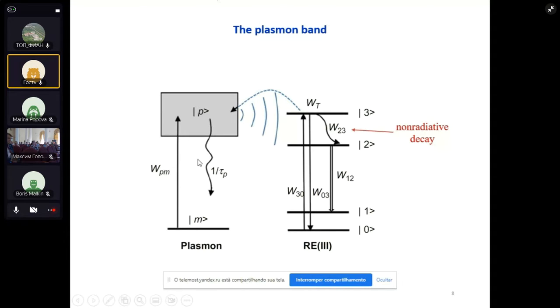And you may ask, why not energy transfer from the plasmon band to the emitting ion? It's because in an appropriate system of rate equations, you'll see that once the lifetime of the plasmon band is extremely short, the energy transfer process from the plasmon to the emitting species is not operative. We can see this in an appropriate system of rate equations.